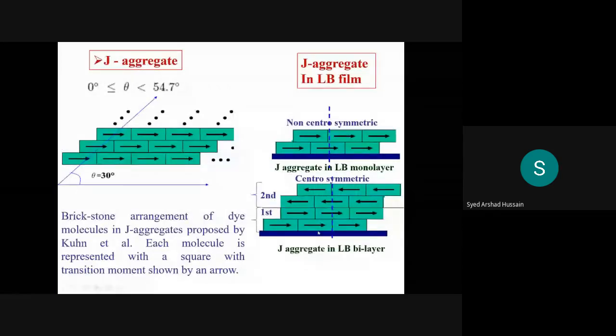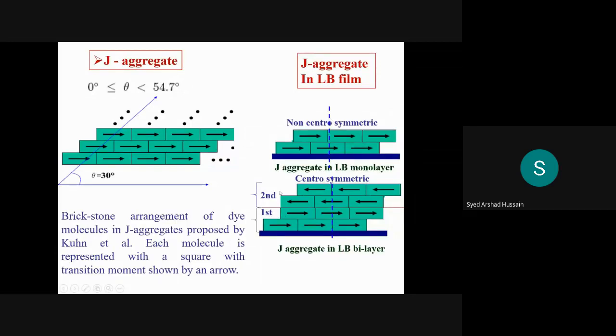So you see, we did some J aggregates using LB film. This is, you see, two layers of the molecules in J aggregates in LB systems. In the first layer, two molecules are stacked, and if you draw a line, you will see it's non-centrosymmetric across this line. But if you prepare another layer upon the first layer, then you see this part and this part are similar, so it's symmetric. So if you prepare even a symmetric molecule in one layer, maybe a stack of more than one molecule, it does not matter, because the aggregates are head-to-tail arrangements of molecules in a specific order. So if you prepare one layer, even with more than one molecule stacking in J aggregates in LB film, then this is a non-centrosymmetric structure and one can have SHG activity.